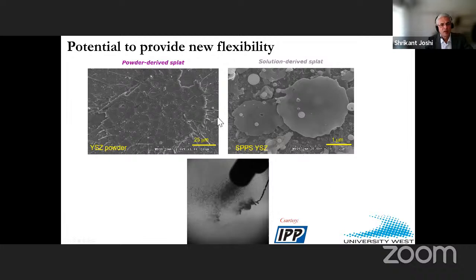When I talk about building blocks, humor me for a minute and look at a typical splat which is powder derived, right? If you look at yttria stabilized zirconia, 25 microns end to end, right? And look at these YSZ splats which are derived from a solution precursor. 1-2 microns max, right? So you're almost 2 orders of magnitude smaller, right?